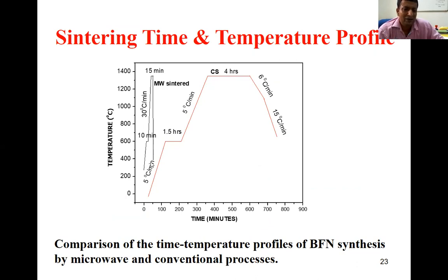This slide is talking about only the sintering profile actually. Let me first talk about the conventional heating. We heat up, there's a holding time for the binder burnout. Then we again heat up, and the holding time is normally 4 hours, depending on the choice of the material actually. And then of course the cooling is there. We have to cool, and so roughly the time comes out to be near about 13-14 hours in the conventional sintering process.